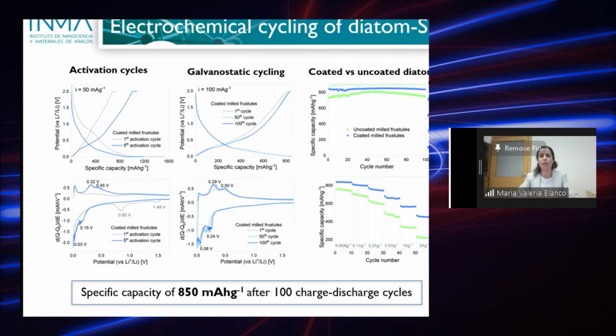So in the upper figures, you will see the profiles of the charge-discharge experiments, galvanostatic cycling, and on the lower part you can see the differential capacity plots. And what is very interesting from these differential capacity plots, where one corresponds to the activation stage and the other corresponds to the galvanostatic cycling stage, is that you can see the emergence of some peaks. And those peaks are related to silicon lithiation and delithiation, which means that this is really happening, that the silica is converted to silicon, and this silicon starts to react in this matrix of inactive species.